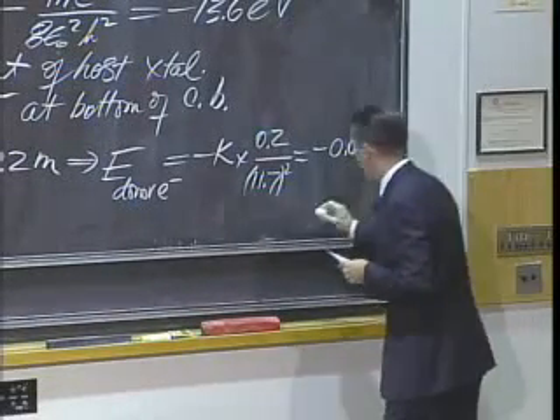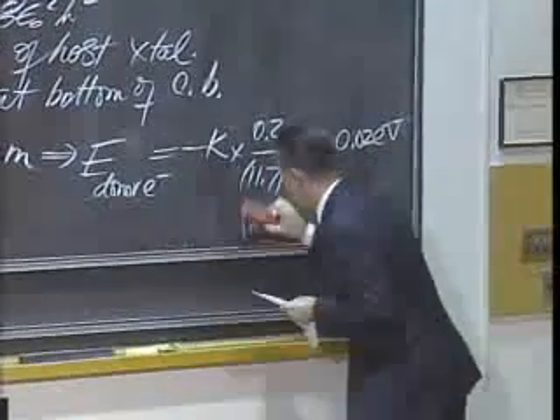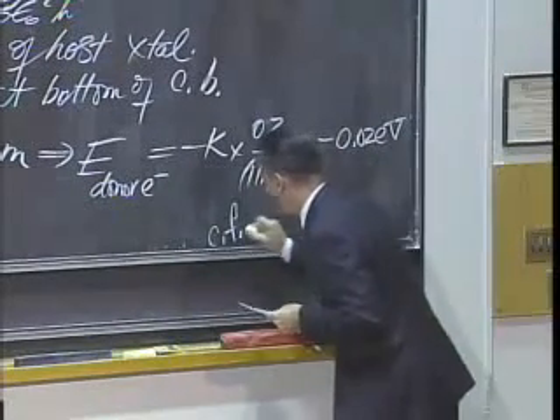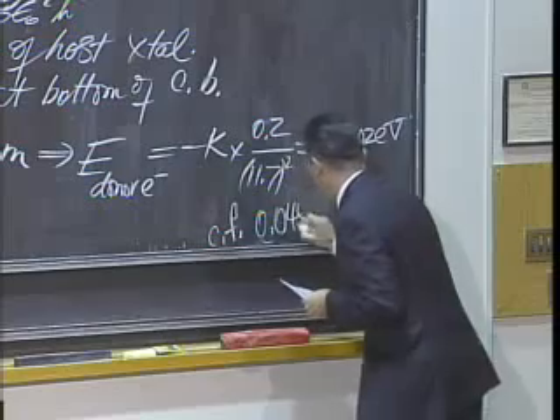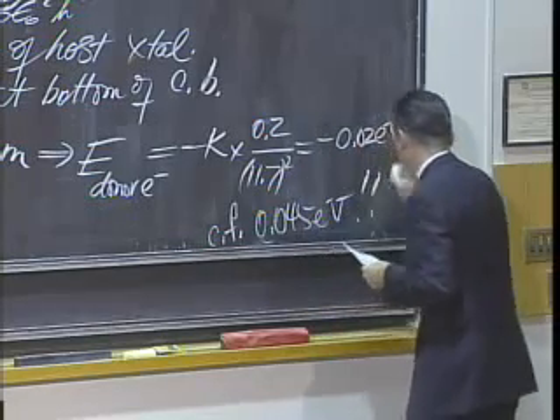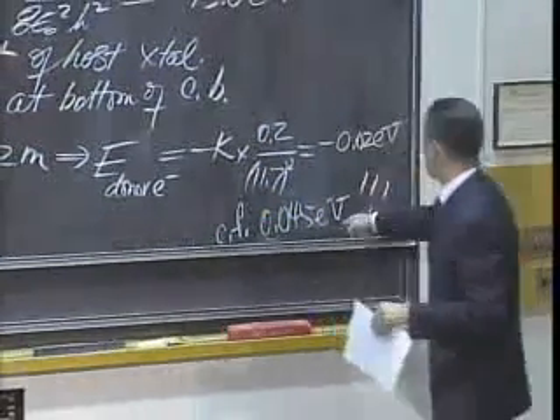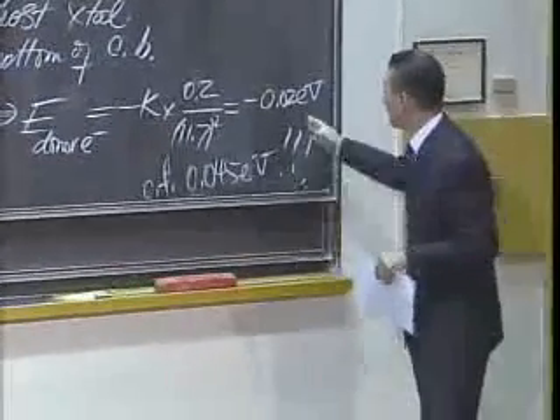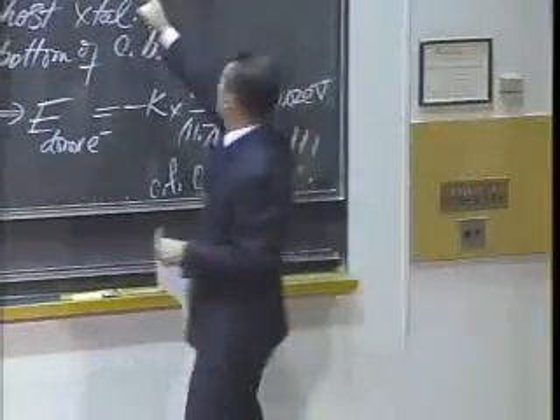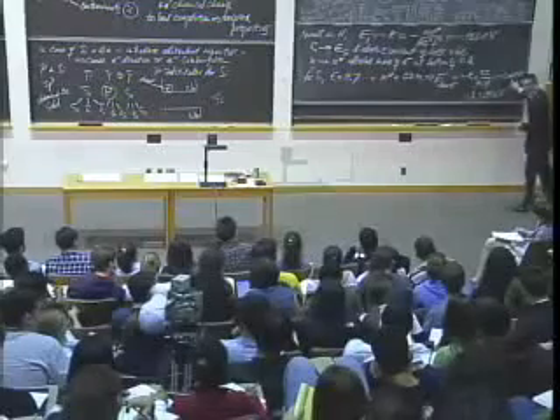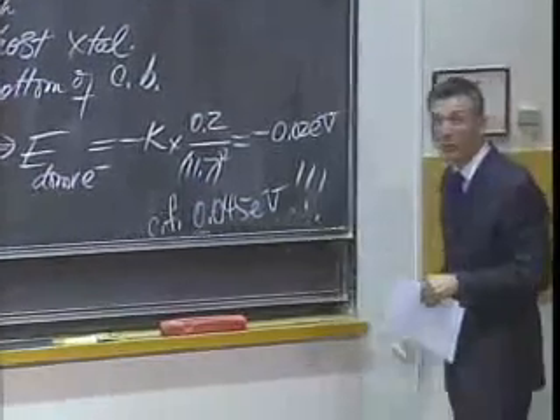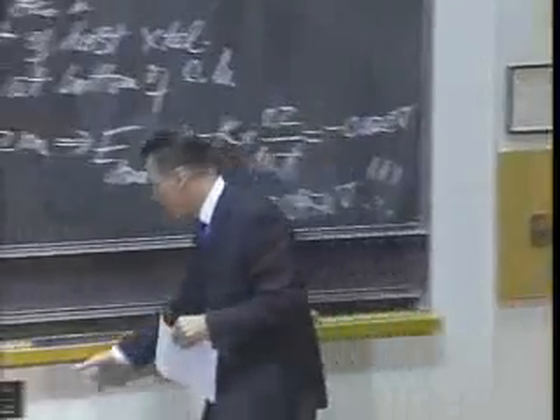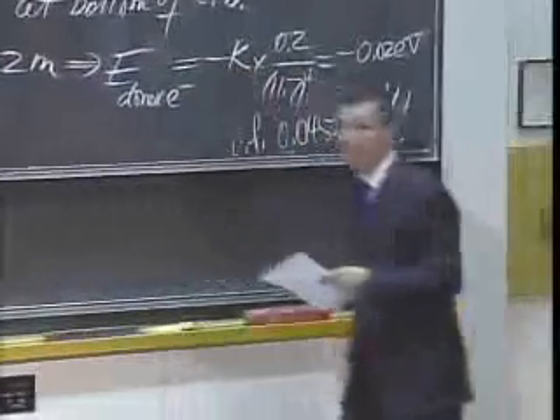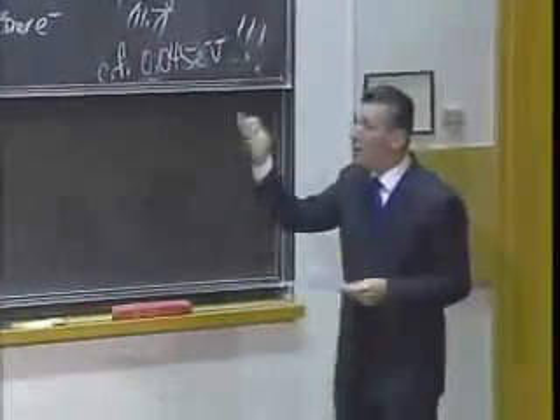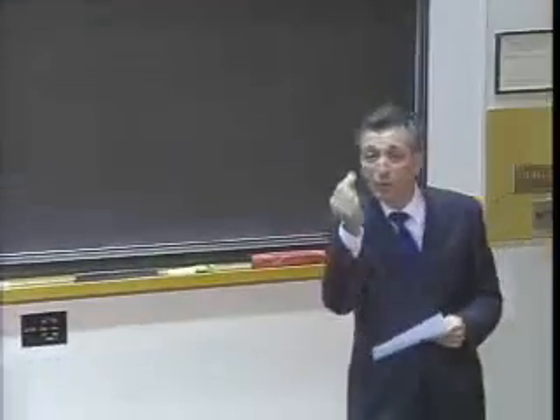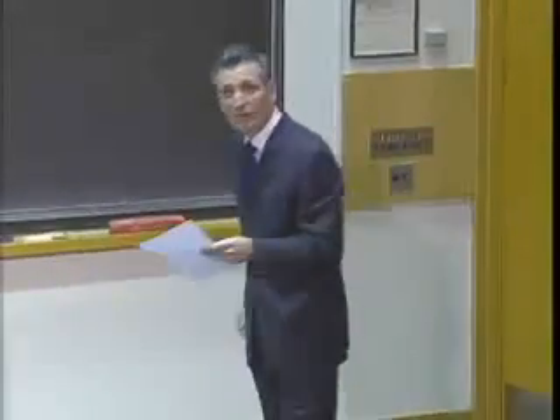The measured value, compare with CF. CF 0.045 eV. Measured. And you might say, well, that's more than double that. And I'll say, but wait a minute. You know, we started at 13.6 and I took it down to 0.02, and you're telling me, yeah, but the real value is 0.045. I said, you don't appreciate good work. This is fantastic with a simple, primitive Bohr model and 2 minor corrections to zoom into condensed matter and give this value.